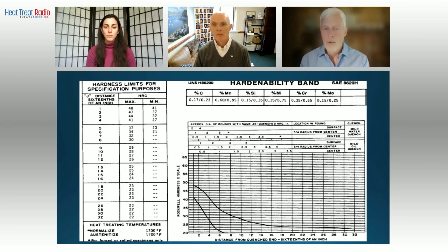As I mentioned before, the domestic sources are very consistent in the material that they produce. To produce a heat of 4320 that's got a J3 of 40 or 42 or 44, there's essentially, in my experience, and I was involved in a major automotive supplier, experientially, no cost penalty to that. It's a definition of what you want. So they're not making heats by randomly selecting chemistries for these heats and selling them.